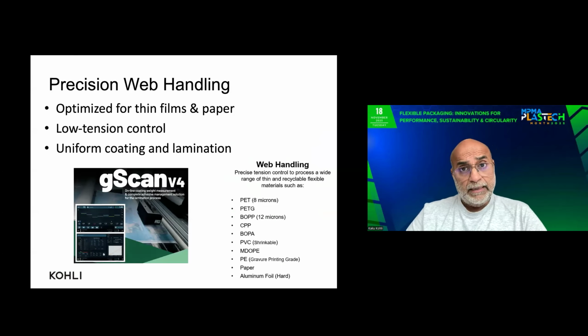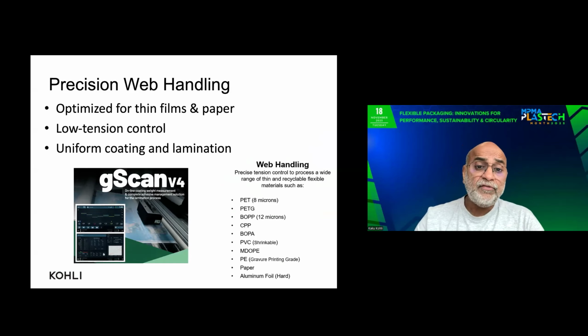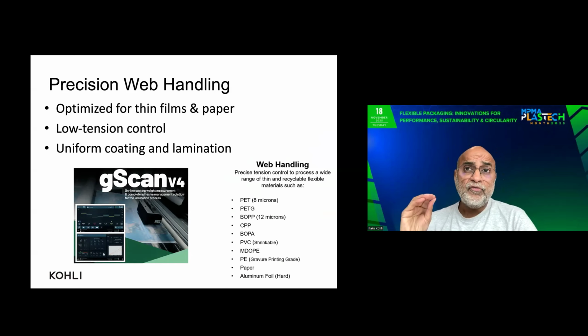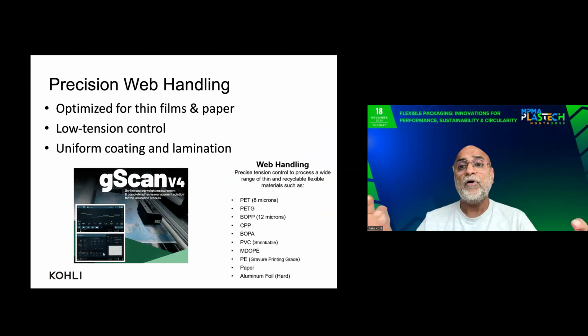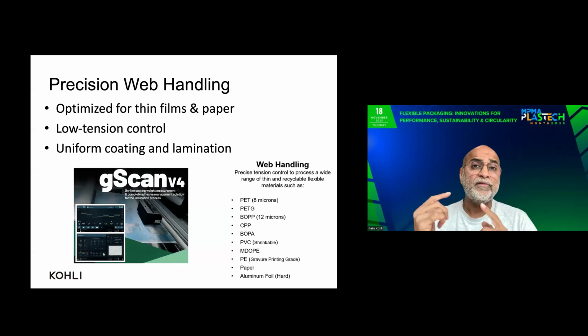Precision web handling is very important as films are getting thinner and you're using paper. The machine should be able to operate at high production speeds with very, very low tension control. And as you see here, we have scanners available today in the market, which can be mounted on a coating machine or a laminating machine, which will help you to reduce your coat weights and be sure that you're getting a uniform coating across the web width, across the length of the web in high-speed production.